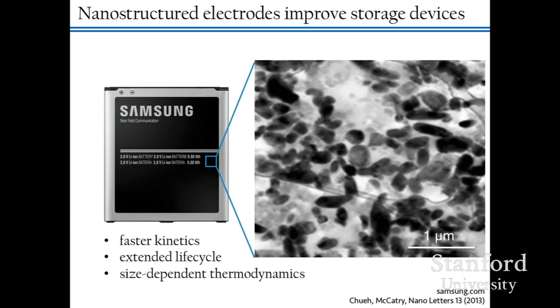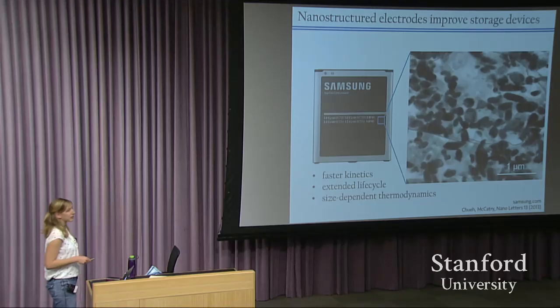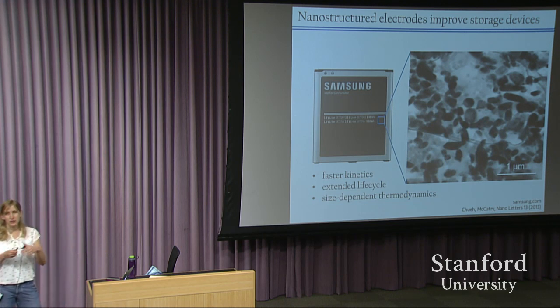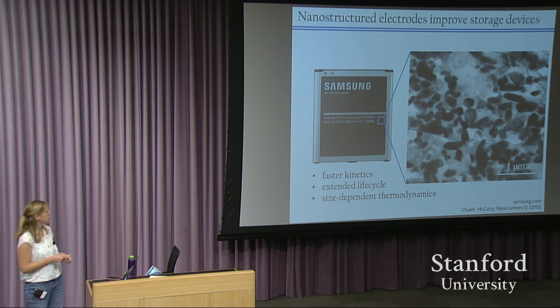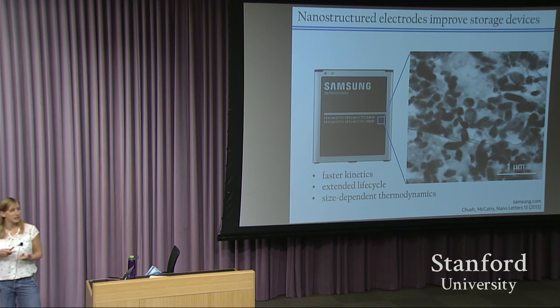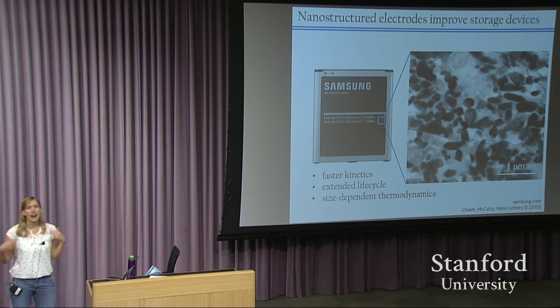So if you look at a big picture of how a lot of energy storage devices, including batteries and fuel cells work, generally ions are intercalating into a host material, into an electrode, allowing that energy to be stored. And if you take a scanning electron micrograph of the interior of a battery, such as the Samsung battery, you'll find that the electrode is composed of a lot of nanoparticles. So ions aren't just going into a bulk matrix, allowing energy to be stored, but generally they're going into nanoparticles. And that's because it's been found heuristically that these nanoparticles, first of all, have faster kinetics, so you can get the ions into and out of the material faster, allowing your battery to charge up faster.